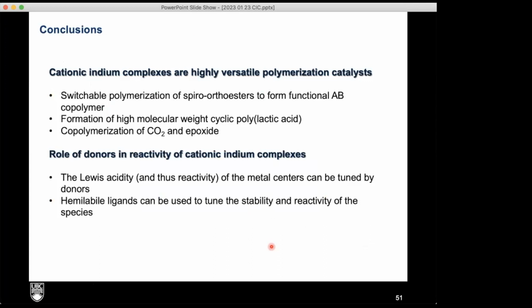and I hope that I have shown you that indium complexes and cationic indium complexes in particular are really versatile catalysts for polymerization, that we can really use them to control the composition of catalysts, that we can play around with the different blocks, different molecular weights. We can really tune and control polymer functionality with these. We can form high molecular weight cyclic polylactic acid, which is a very unusual and high molecular weight in particular is relatively unknown. We can generate copolymers of CO2 and epoxide. And then I showed you that we can really tune this reactivity by what the donors are.